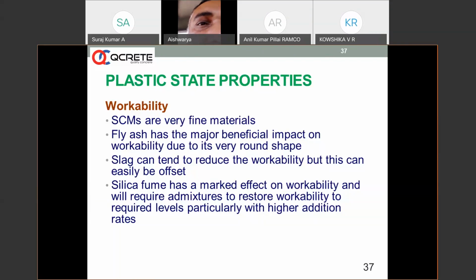Slag tends to reduce the workability, but this can easily be offset. Even though, for example, from an OPC mix to a slag mix, where we shift from OPC mix to 50% GGBS, definitely you have a slight water reduction, but not as good as what we can achieve with an OPC fly ash mix. So OPC fly ash mix gives the best water reduction, followed by OPC GGBS, and then the highest water cement ratio is what we encounter when we are using OPC.